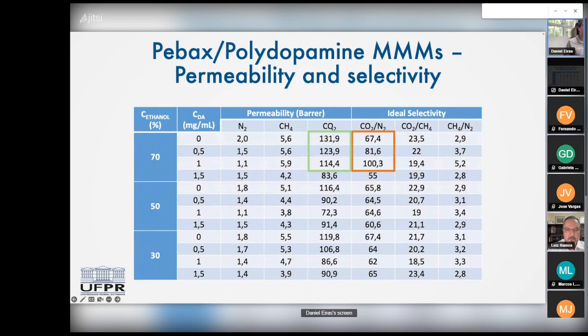The results we get are in this table. As you can see, the permeability of CO2 is reduced with the incorporation of polydopamine. So this is the concentration of dopamine hydrochloride that we have here. We are increasing the concentration, and what happens is that the permeability is reduced. At the same time, the selectivity is increased. So basically what we did is that we got part of our work done. We get to increase the selectivity, but we reduced the permeability, which is unfortunate, but okay, it happens.